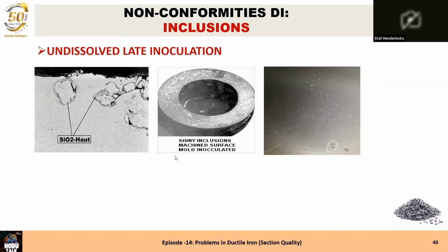Sometimes you see it on the left side. You can see it under the microscope. It was the SiO2 which was not solidified. In the middle, you see a casting which was machined, and you find out that some shiny inclusions were there. That's also inoculation. On the right side, that's very few, but it's also there. You see all these white spots all over. That's inoculation which is not dissolved properly.